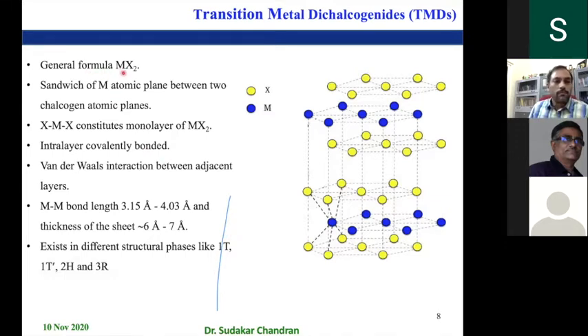So, the transition metal dichalcogenides have a general formula MX2. The metal atom layer, for example, the one shown here in blue, is sandwiched between the X layers, where X is sulfur or selenium, MoS2 or MoSe2. So the metal layer is sandwiched between these sulfur or selenium layers, and it gets stacked up. So this is one monolayer, and two layers are shown here. The metal to metal bond lengths are typically in the range of 3.15 to 4.03 angstrom. The sheet thickness is roughly about 6 to 7 angstrom. The distance between the sheets is also around that same distance.